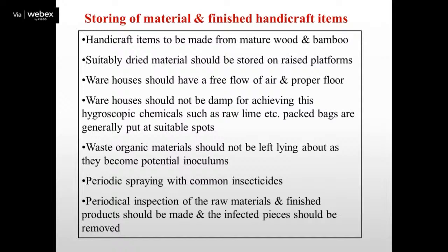For achieving this, hygroscopic chemicals such as raw lime or silica gel packed bags can generally be put in suitable spots. Waste organic material should not be left lying about, as it becomes potential inoculum. So periodic spraying of common, mild insecticide can be done in the warehouses. Periodic inspection of the raw materials and finished products should be made, and infected specimens can be removed.